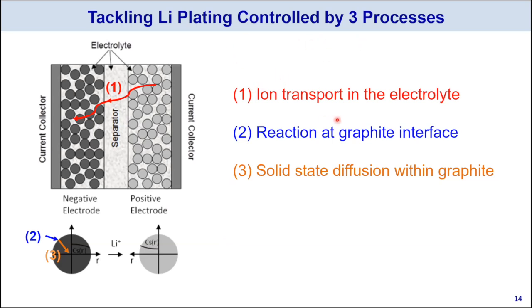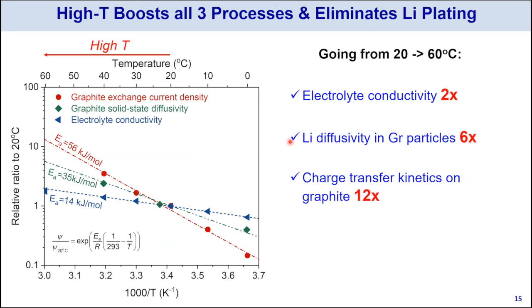As we know, it's all controlled by three processes: ion transport through the very thick negative electrode in the electrolyte, then the charge transfer reaction at the graphite surface, followed by the third step, which is lithium atom diffusion in graphite particles. All those three processes can be greatly enhanced by higher temperatures, as shown by the data here. But the simple message is that if we go from 20 to 60 degrees Celsius, in other words, thermal stimulation, we will acquire a novel electrolyte, as if, with doubling conductivity, and we will create a novel graphite material with six times improved diffusivity within.